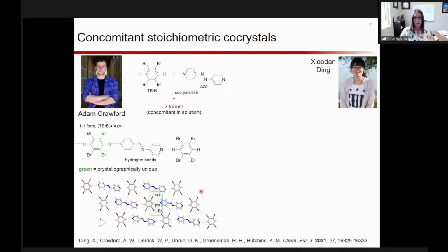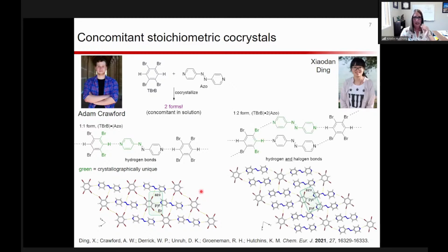The second form was what we actually did not expect to get. And so in this case, what we have is a 1-to-2 form. So we have half the unique tetrabromobenzene, but now a full unique molecule of the azopyridine. So we do have the CHN hydrogen bond that we initially expected, but now on the other side, we have a halogen bond with the bromine instead of the CHN hydrogen bond.